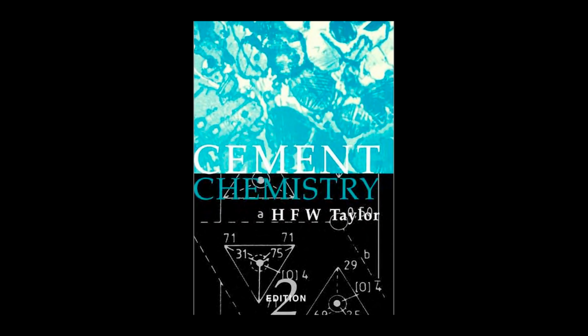Yes. The lowered pH triggers an aggressive decalcification of the CSH gel. The CSH loses its calcium, and magnesium integrates into the structure, forming a magnesium silicate hydrate, which is structurally similar to poorly crystalline serpentine. This material has no cementing properties whatsoever. Wow. This entire process leads to physical softening, a complete loss of cohesion, and the ultimate destruction of the concrete structure, often leaving behind only a friable silica gel.